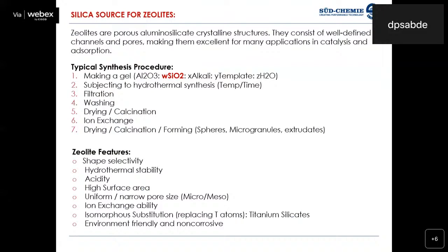These zeolites find applications in many areas, which we will come to next. But what is most important to know is how silica is actually used in zeolites. If you look at the synthesis procedure of a zeolite, there is an alumina source, a silica source, an alkali source, and a template. The template is nothing but a structure directing agent, normally we say, and there are also certain molar ratios for water. This combination we call the molar gel recipe. It is subjected to hydrothermal synthesis at a particular temperature, anywhere beyond 150 degrees depending on the kind of zeolite we are making, for a particular time, and subsequently after cooling down we do filtration, washing, drying, and calcination. And this zeolite in the as-synthesized form has the alkali associated with it.